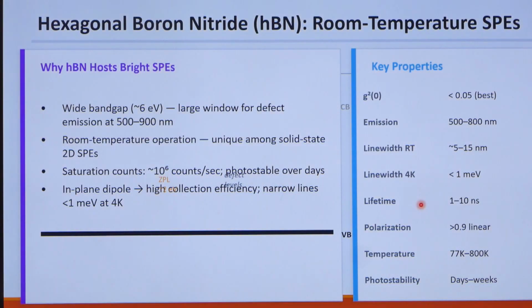So hexagonal boron nitride, I have said from the beginning, is very widely used, but normally you will say it is an insulator, so how will it give any luminescence? But inside the insulator, with a band gap of 6 eV, you create energy levels through induced defects and control the energy level in between. So in that case you will find emission in the range of 500 to 800 nanometers, which was the ZPL, the zero phonon line, meaning directly from top to bottom, with no phonon. Then the lifetime is this much, and the temperature is 77 to 800 K. So a wide band gap gives a large window for defect emission, and room temperature operation. The advantage is that if anything can be done at room temperature, it is always good, right?